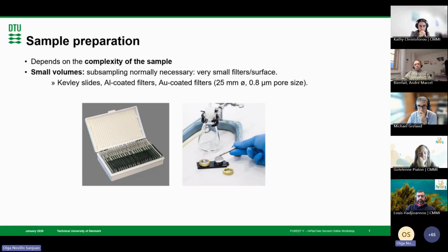But I would say in this sense, normally if you go through a full sample preparation workflow like I showed before, then it's better to use the circular and aluminum coated ones because you get rid of some steps. If you use the Kevley slides, you need to filter previously with GCF filters, for example, and then you have to ultrasonicate these filters and go through a series of additional steps that increase the risk of sample loss. So the advantage of these aluminum coated filters is that you directly filter everything in that filter, so you don't lose sample.